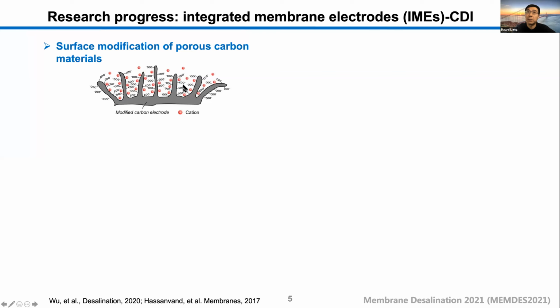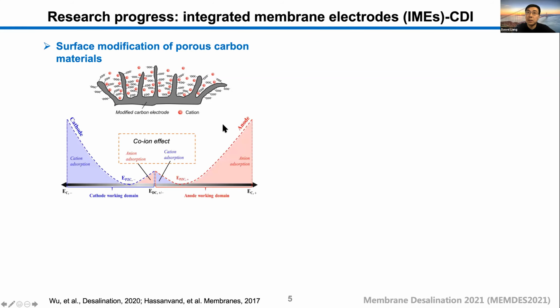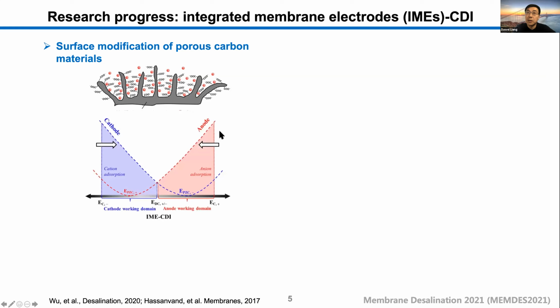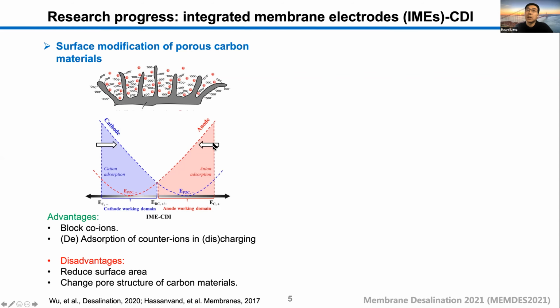The first is surface modification of carbon materials. Just now I showed you the mechanism of the co-ion effect, but you could also use surface modification to change the EPZC. For example, you make the EPZC of the anode shift negatively to lower than the discharge potential, and make the EPZC of the cathode move positively, larger than the discharge potential. So it could only absorb the counter ion and desorb during discharging. But the disadvantage is that it will reduce the surface area and change the pore structure of the carbon material.